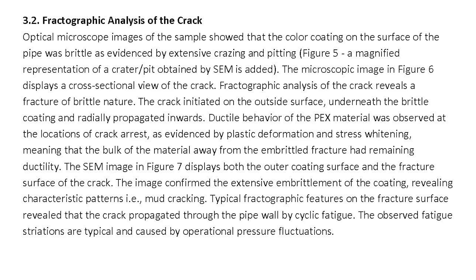As evidenced by plastic deformation and stress whitening, the bulk of the material away from the embrittled fracture had remaining ductility. The SEM image in Figure 7 displays both the outer coating surface and the fracture surface of the crack. The image confirmed the extensive embrittlement of the coating, revealing characteristic patterns of mud cracking. Typical fractographic features on the fracture surface revealed that the crack propagated through the pipe wall by cyclic fatigue. The observed fatigue striations are typical and caused by operational pressure fluctuations.